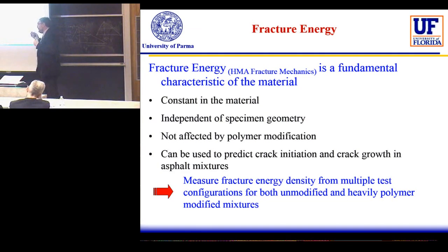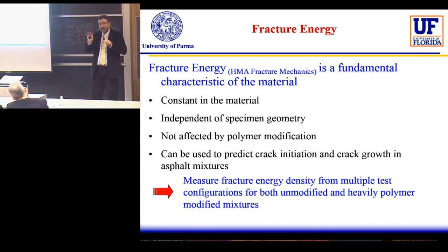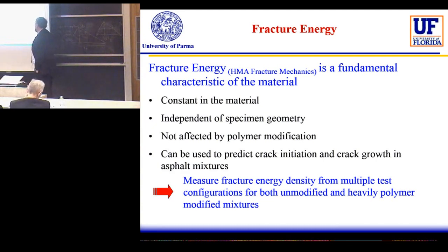So the hypothesis was that by changing the internal property of the binder, it was possible to have a change in the general behavior of the material, and maybe the approach could not be identified and the basic hypothesis must be adapted to this internal change of the material. We were able to show that the hypothesis was still valid even with the change in the fundamental property of the material. For that, we measured the fracture energy density from multiple test configurations in both cases of material, unmodified and heavily polymer modified bitumen, with different amounts of polymer inside the bitumen, and so different mechanical behavior of the material.